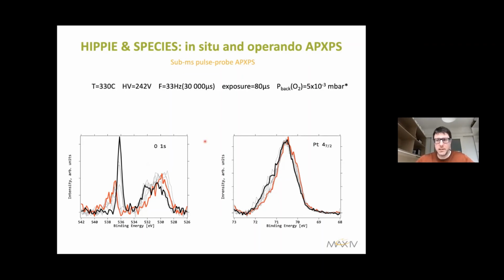The oxygen-rich phase is a little bit puzzling for me. It seems like we have oxygen adsorbed on the platinum, and it overlaps very nicely with the literature data. But then looking at the platinum, instead of having oxygen or even oxide sitting on platinum, which would appear at high binding energy, we have a reduction in platinum. So it seems like we clean our platinum, or there is another good interpretation. If you have good ideas, I would be very glad to discuss them with you. But anyway, we can now correlate the components and the composition of the platinum surface by fitting these features